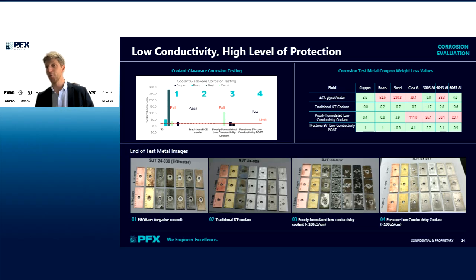If we put a traditional high conductivity internal combustion engine coolant through this GB specific glassware corrosion test, it passes the test no problem, right? And this isn't a surprise. We know that the Prestone coolant is very robust, but it won't meet the spec because the conductivity is over 100 microsiemens.